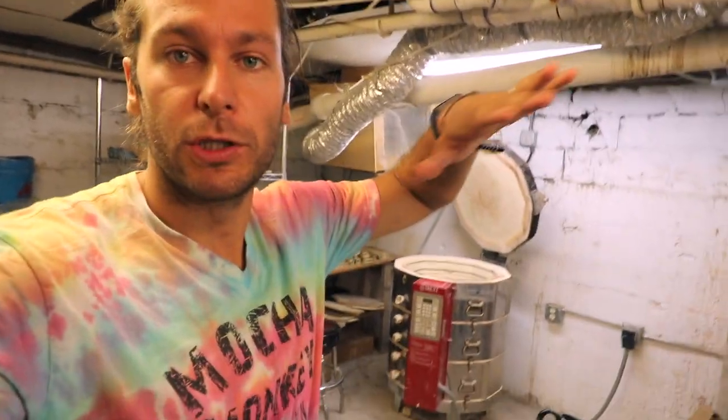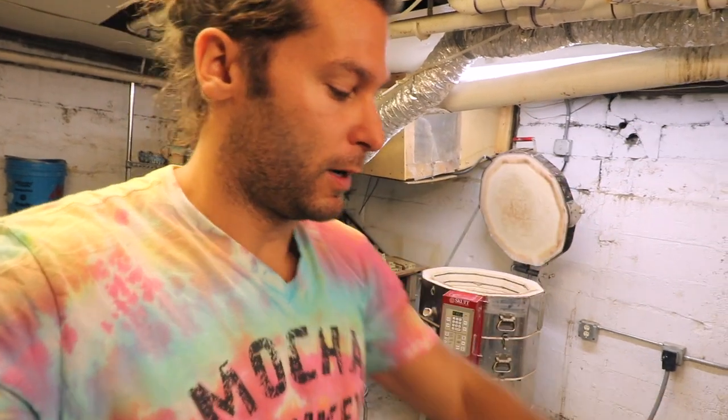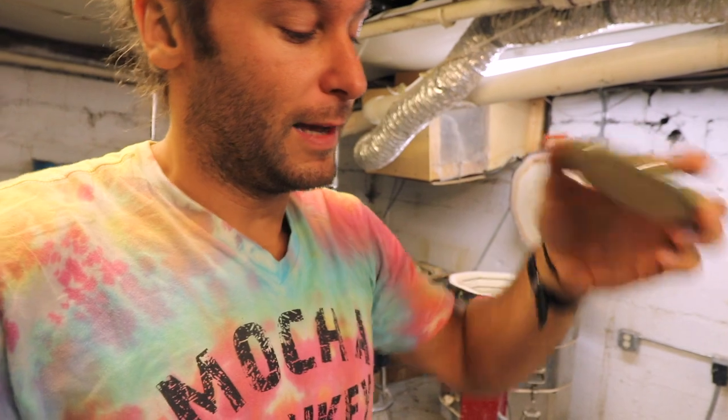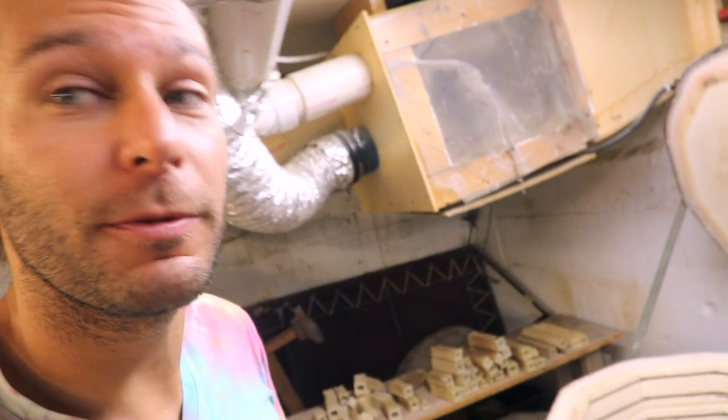And so far my theory has held up that making a gradual slope on the edge of this and then not putting too much glass in there. I haven't broken any since I've really started doing that. So I think that's the key. So I hope that helps you with your glass coasters. And if you tried them before and they didn't work, I encourage you to try them again because they're super fun and super cool. And they take up no space in the kiln.